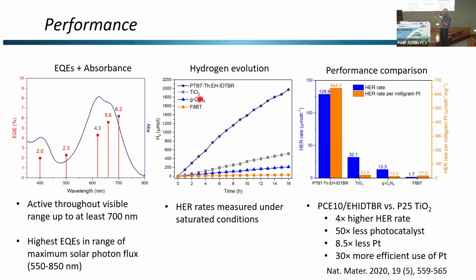But if you compare it to the conventional technologies, this was the best polymer that was out there. This is carbon nitride and this is titanium dioxide. So these were the two benchmark materials. And you can see that our heterojunction dramatically outperforms them on overall HER rate, but also maybe more importantly, HER rate per milligram of platinum, if you start to think about the cost and the use of rare earth metals. So we were able to deliver on that.